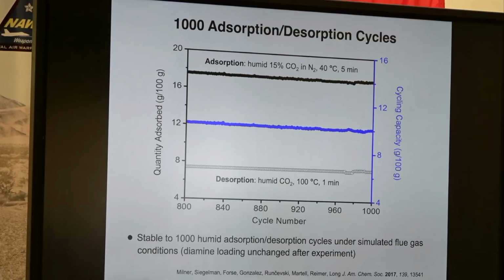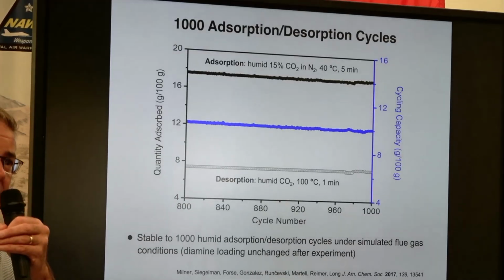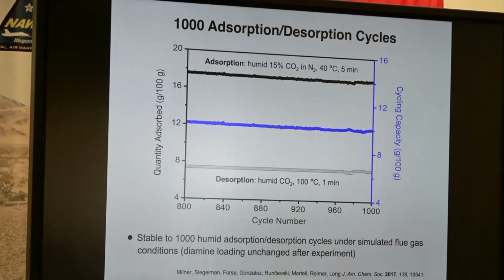This is the last 200 cycles. Here we're adsorbing at 40 degrees C from a simulated coal flue gas, and then releasing at just 100 degrees C. And you're not seeing any degradation of performance in this experiment. So this is at 40 degrees C capture, which is standard for aqueous amines. There's a big advantage if you can capture at higher temperatures. You don't have to put all this energy into cooling the exhaust gas coming off at enormous rate from these power plants or from other combustion sources.